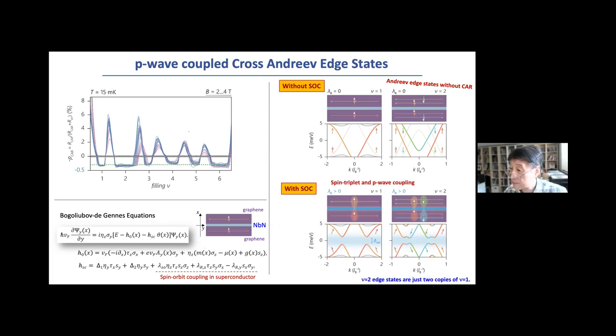Why is the CAR probability so small, about a few percent, about 1% or 0.5% in this particular case? It turns out that as soon as you include some barrier-like term, in this particular case, co-tunneling of the carrier spoils this process. You quickly start to reduce this CAR probability, and typically the Z number we include there is something like about 0.5-ish. Then you get about a few percent of the Cross-Andreev process happening here.